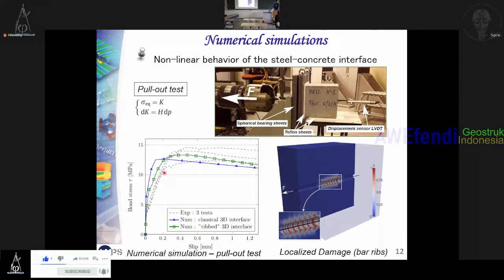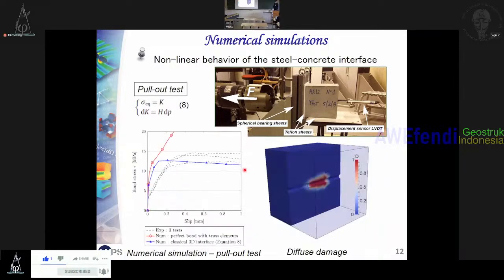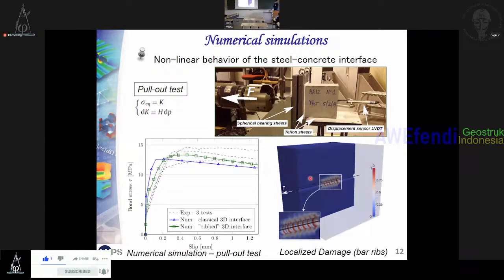But with this type of model, there was a better reproduction of bond strength with respect to slip, but also if you look at the damage, representative of the cracking, with this type of model you can see that you have uniform damage. With this new model, you can retrieve what Dirk just showed before, cracking appearing at the top of ribs. So it's not more complicated. Of course, you add some parameters, but you are more able to predict cracking, and also bond stress versus slip.